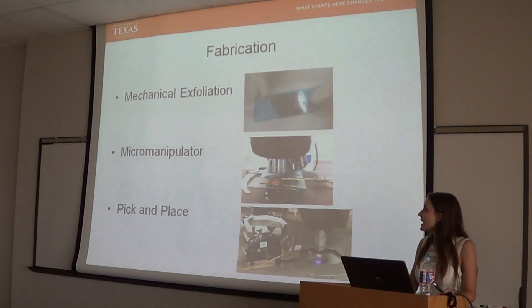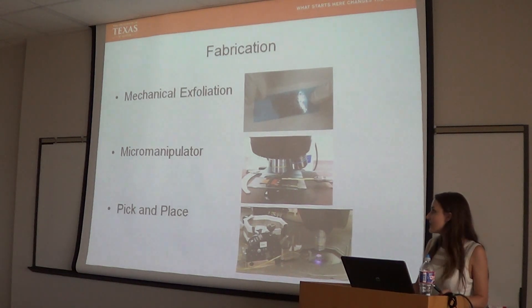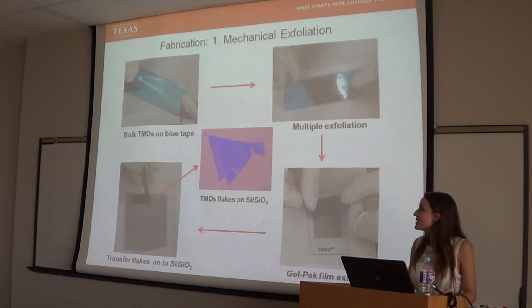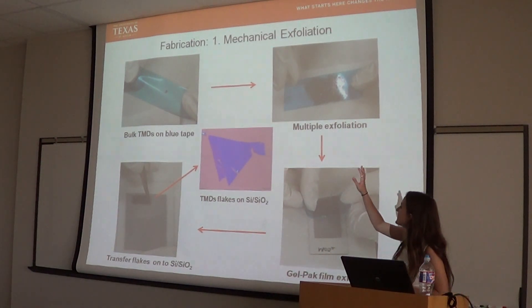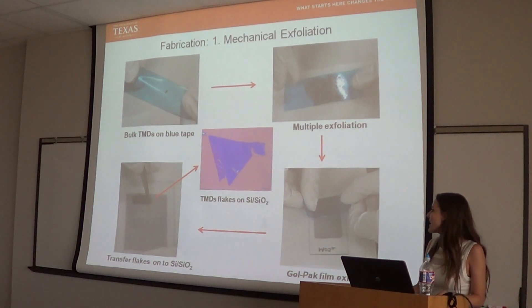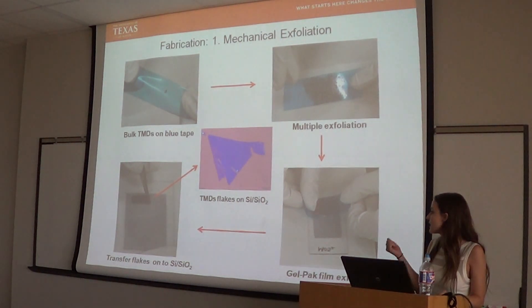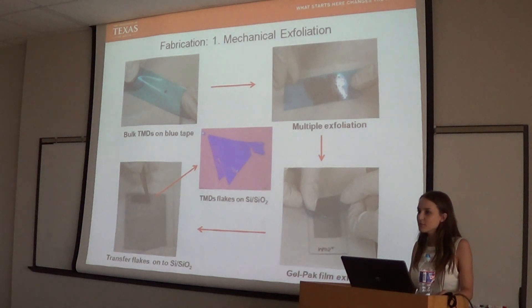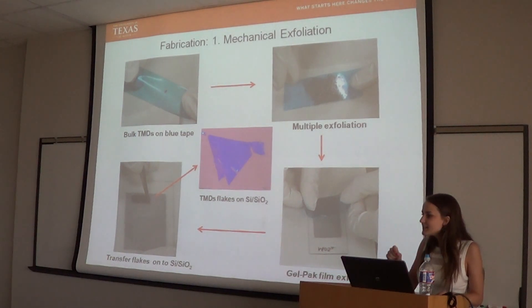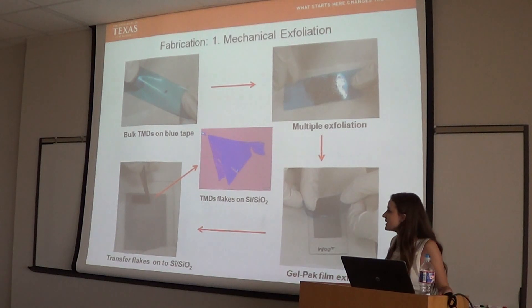How do we fabricate these heterostructures? First, we have mechanical exfoliation to create the monolayer of the TMDs. You place a little bit of your bulk TMD in the middle of blue tape and simply separate it layer by layer, since it's held interlayer by van der Waals forces, until you have lots of flakes all over your blue tape. You can't see when you've achieved monolayer — it's too small — but once you think you have, you place your tape onto the gel pack to create a larger area of flake and reduce tape residue. Then you transfer it to your silicon-silicon oxide wafer by placing the wafer on the gel pack, tapping the corners, and removing it with tweezers. Here's an image of a flake on your silicon-silicon oxide wafer.